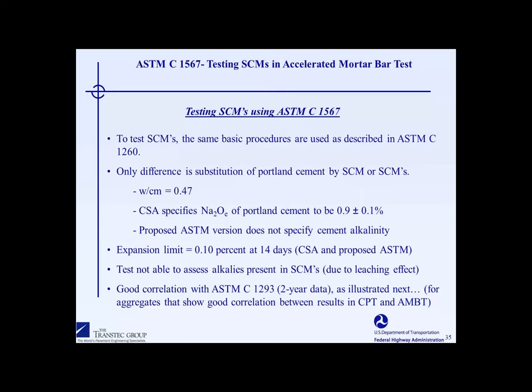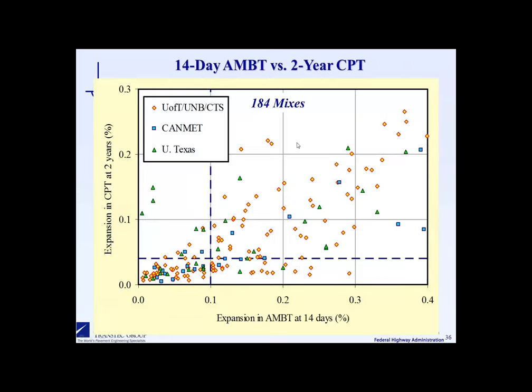Generally speaking, there is a reasonable correlation between the results of this test at 14 days and the results of the concrete prism tests after 2 years of testing. And I'll show you here, this is kind of a data dump of a bunch of different results from our various labs. And what you'll see here is that there are quite a few aggregates that are the good actors. They're giving us reasonable correlation here where we're getting pass. Both test methods are resulting in passing results in the lower left and in the upper right quadrant.